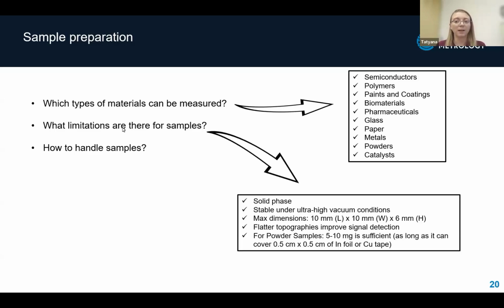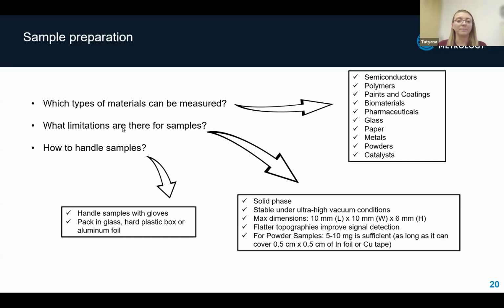The only requirements are it should be solid, stable in ultra-high vacuum conditions, and there are some limitations for sample size. Also, it should be mentioned that for better results, the surface should be as flat as possible. How to handle the samples? The samples should be handled with gloves and packed in glass, hard plastic, or aluminum foil.